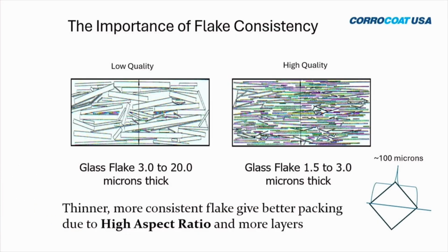When we first started in the 70s, we used glass flake that was a byproduct from Owens Corning. So they basically classified their waste. You melt it down, you inject the molten glass with air, it explodes, you have bubbles, then you classify again to get the different sizes of glass flake. It's a crude method for making glass flake, and it leaves you with a wide variance, 3 to 20 microns thick. It still works. We have a lot of competitors that still use this type of glass flake. It works to a certain extent.